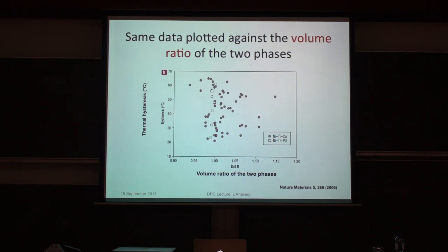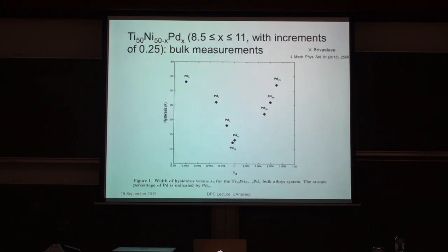So determinant U is 1 means there's perfect volume conservation of the phase transformation. But now you plot hysteresis and you see that, this is in fact old data before these very low alloys, but anyway, you see that some of the alloys with the lowest hysteresis and the highest hysteresis have the determinant 1, have no volume change. So it's quite surprising there's no correlation with the volume change. Okay, so first of all, you have to explain people made huge numbers of these nickel, titanium, copper, and so forth, even palladium, nickel, titanium, copper, palladium, and various other elements before these results. So how could they possibly miss the lambda 2 equals 1 materials?